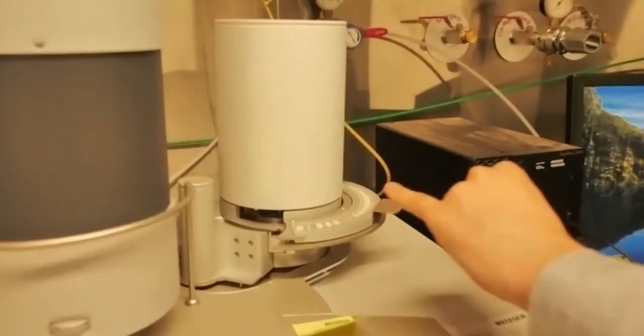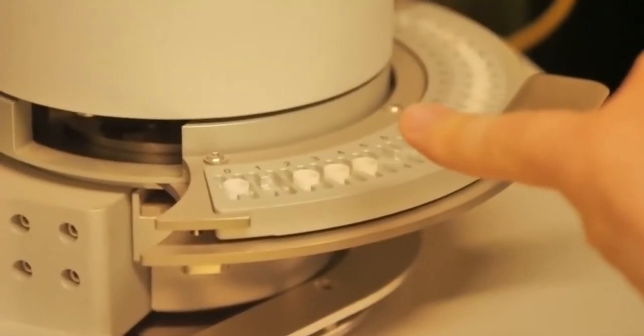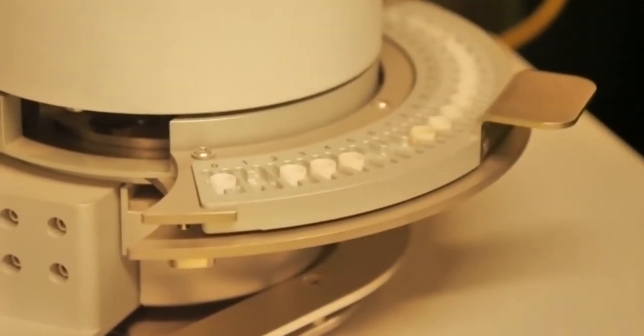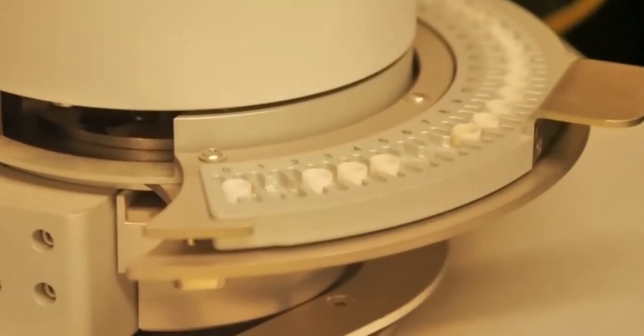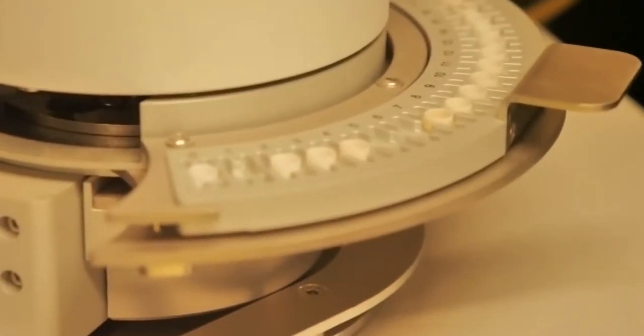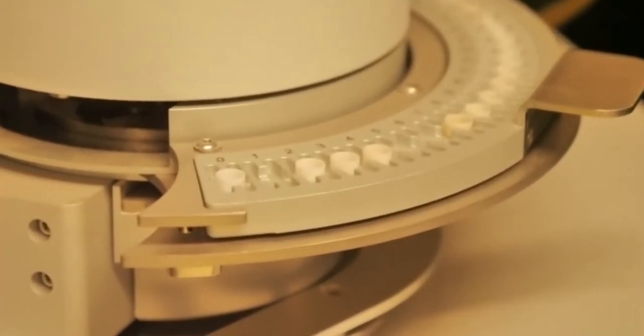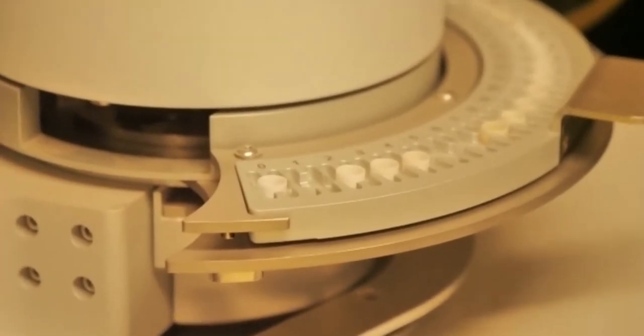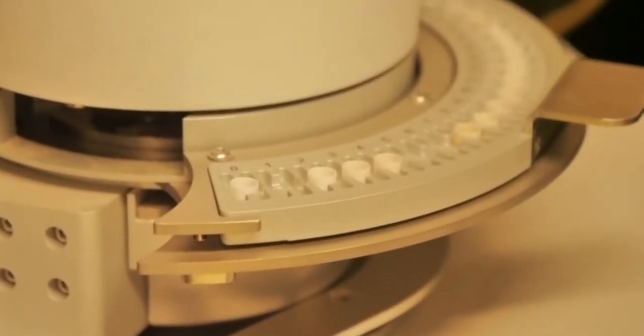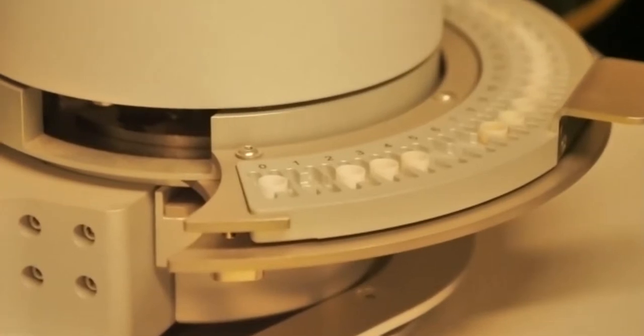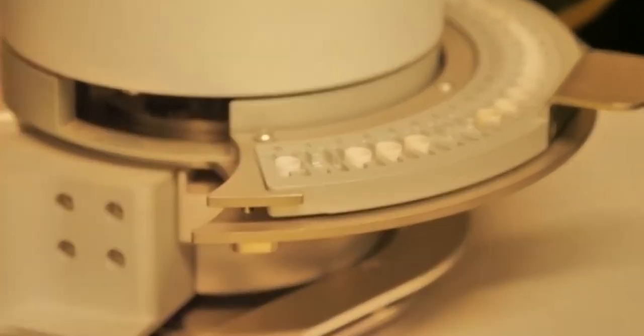As you can see, this is my finger. The amount of material that we place in here is quite small. Why do we do that? Because what we try to understand is if we can decouple the problem of thermal decomposition from the heat transfer. So by testing really small samples, we ignore the heat transfer taking place during the thermal decomposition.